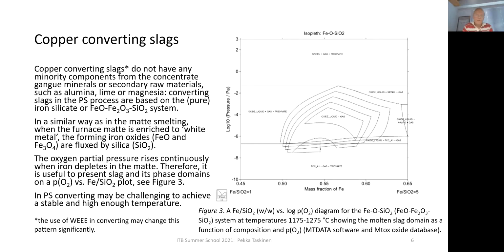So silica, and now the forming converter slags are relatively pure iron silicate slags generated from this ternary system of ferrous oxide, ferric oxide, and silica. So this is now more simple slag. We can predict very easily how it behaves as a function of composition, as a function of oxygen pressure, and as a function of what I could call fluxing rate or fluxing degree, how much silica we are adding in the converter.